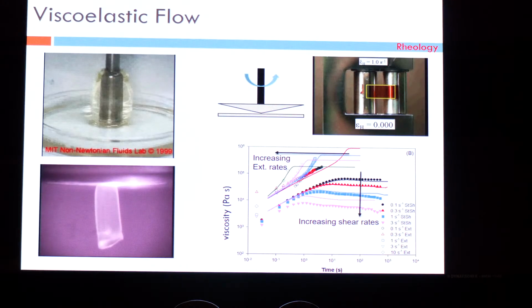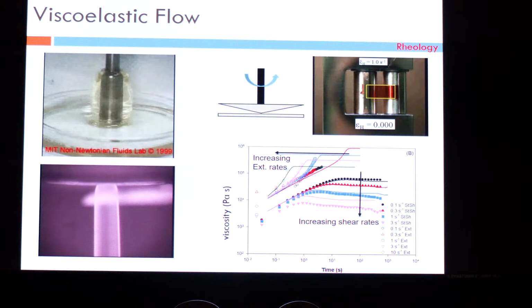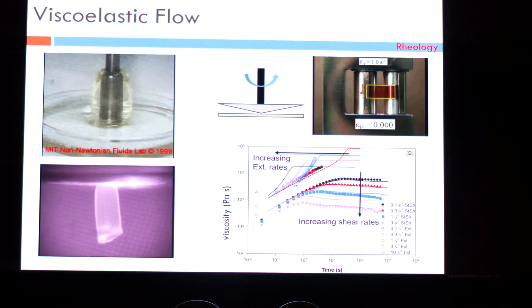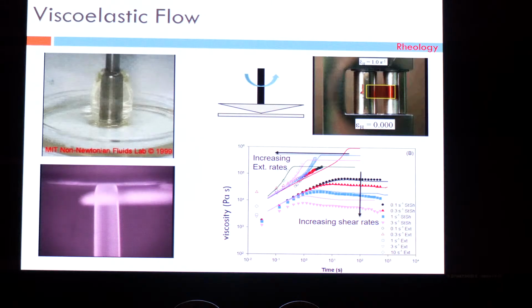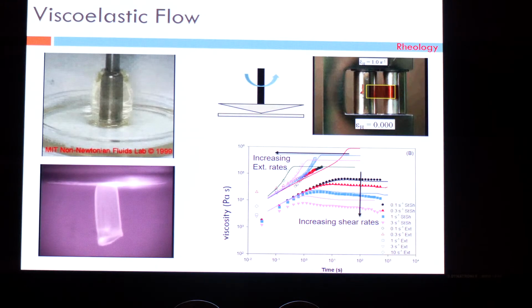And on the top you see two equipments that are used in the laboratory to measure these flow properties. On the left is what is called a cone and plate viscometer. You have basically a flat plate, you have a cone, the liquid is sandwiched between the two, and one of them is rotated, either the cone or the plate is rotated. So you have the liquid which is sheared in between these two plates, and you measure the resistance to shear and convert that resistance into a property called the viscosity.